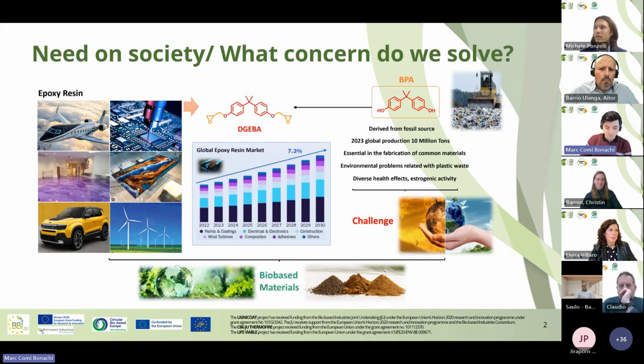The growth of the epoxy resin market in the next 10 years is going to be up to 7.3%. That means that the use of this bisphenol is going to increase, and this represents a problem not only for the landfills, but also because part of this bisphenol A that is not reactive during the glycidylation process can migrate during the use of the material and can contaminate the ecosystem and also humans. It has been detected in different studies in Canada, in Australia, in USA.